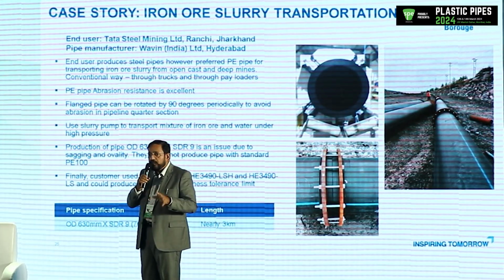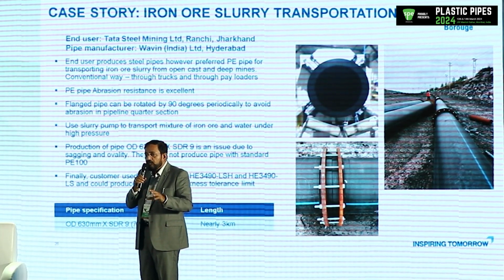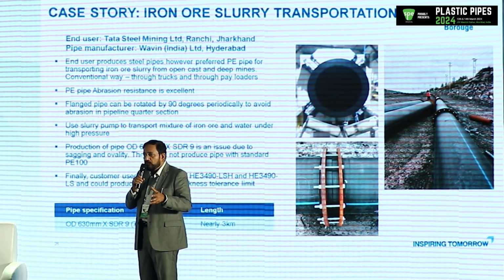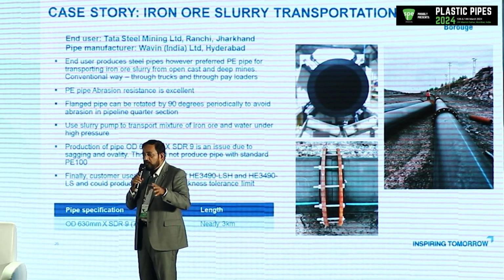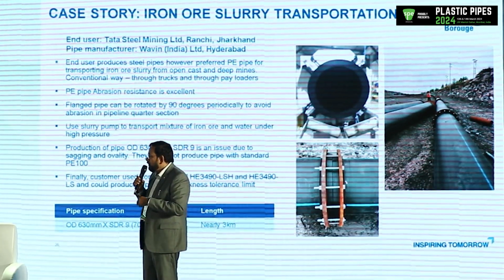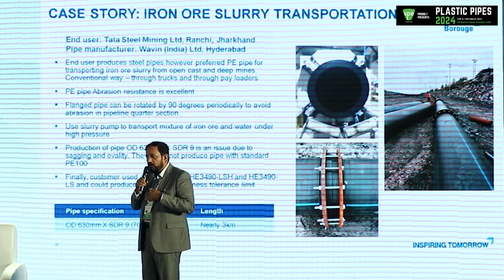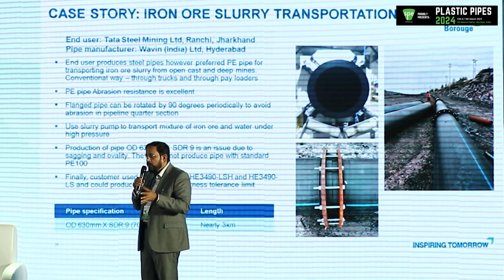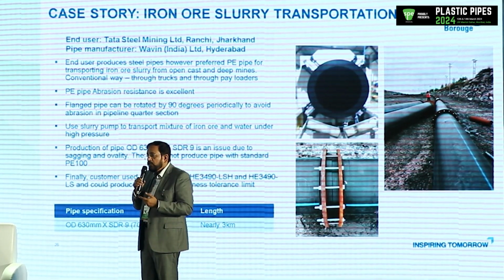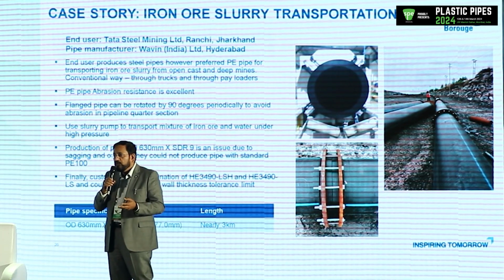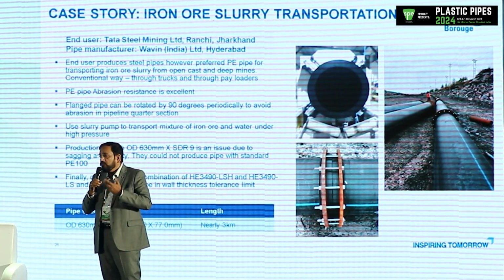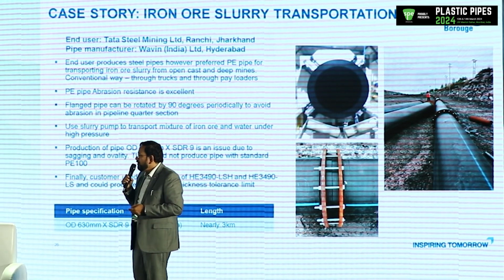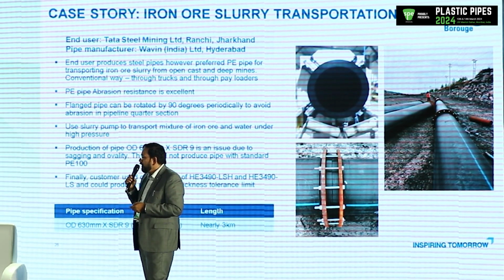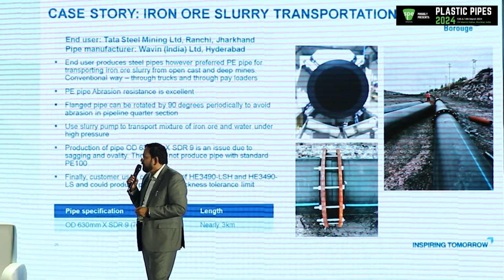And then they start rotating the pipes, say 90 degrees. After some time, they will rotate to 180, then 270, and probably we are back to this. So that you don't keep abrading one section. So instead of having a life of 4 years, you can achieve at least 3 times, that is 12 years. So this is excellent material, and this property can be very useful for this kind of application.